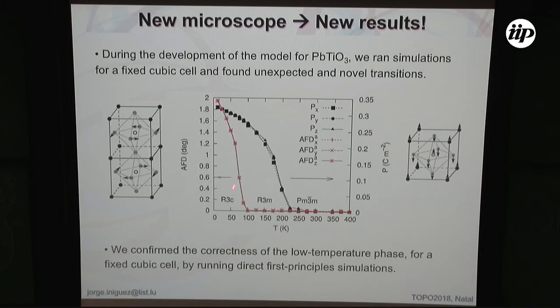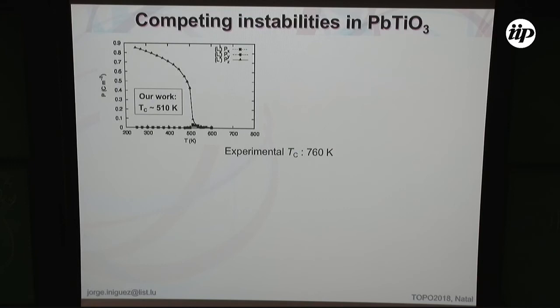We thought our model was probably wrong, so we verified explicitly by running additional ab initio calculations that this is indeed the lowest energy structure when lead titanate is constrained elastically to retain a cubic cell. We fitted our model without this kind of information — this was something we didn't know — but the information we put into the parameters makes the model wise enough to predict things we didn't know in advance. This happens on a daily basis with our models, and it couldn't happen with the previous simpler models.